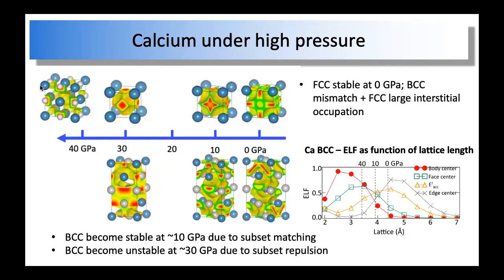So that's the overall reason. It's very simple. And a similar story happens to calcium, except calcium is a little farther away from the perfect matching point for the BCC. So therefore, it starts with FCC structure. But if you compress it, then it becomes subset matching for BCC. So therefore, BCC becomes stable. Remember, if all the lattices are subset matching, then BCC always wins because the split is perfect. And then if you increase the pressure, the BCC again becomes unstable, because it develops very strong subset repulsion, right? So that's the same story.